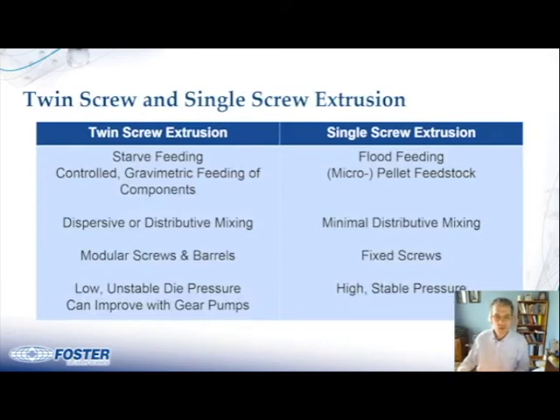So twin screw extrusion and single screw extrusion is sort of a comparison here. Twin screw extruders are starve fed. The feeding is controlled using gravimetric feeding of the components. And in single screw extrusion, it's flood fed. So all the material is put in the main feed throat, and the control of the feeding is not critical. With twin screw extrusion, you have much better mixing and control of mixing because the screw design is modular and the barrels are modular. You have less mixing capability and control with a single screw extruder. You do have some mixing that occurs, but it's mostly distributive type of mixing. And the screws in the barrel are fixed, so they're not programmable or adjustable.